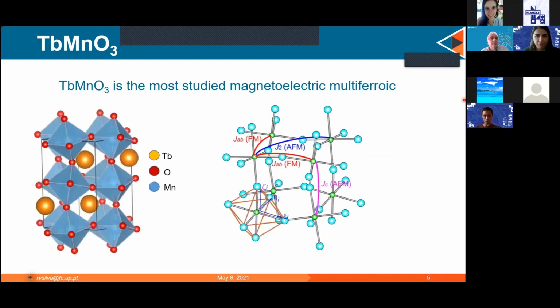So we work a lot with the most well-known and most studied magnetoelectric and multiferroic material, which is terbium manganite. So you have terbium, manganese, and oxygen. You have the manganese, which is magnetic, and it's inside this octahedra of oxygens, and then you have terbium in between. And what happens with this material is interesting because it's magnetically frustrated. So you have different interactions which are ferromagnetic and antiferromagnetic at the same time.